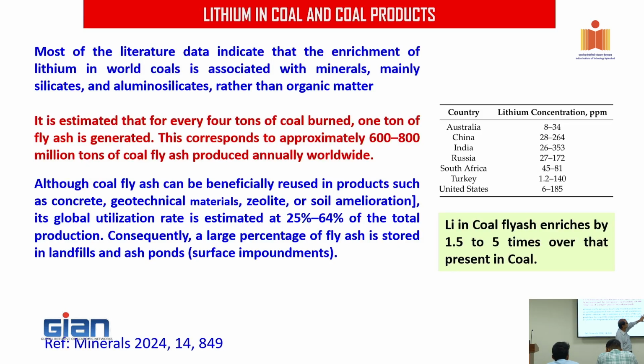coal. Generally, when you put this coal in a boiler, in a thermal plant, there will be enrichment of this so-called lithium 1.5 to 5 times. As it happens in rare earths, 10 times enrichment will be there from coal to coal fly ash. So if 50 ppm is present in the coal, it goes up to 500 ppm. 10 times is the general thumb rule. Here it goes 1.5 to 5 times and gets enriched in the coal fly ash.